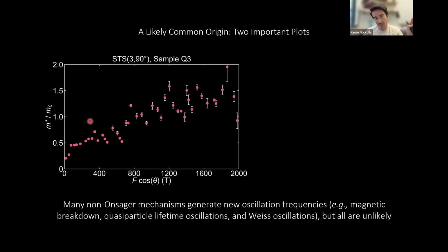There are many of these that are detailed in our supplement, and nearly all of them have very distinctive signatures in effective mass. So if I were to generate 45 different new pockets from magnetic breakdown, I would expect the effective mass of those pockets to skyrocket up to 45 bare effective masses, or plummet down to 1/45th of an effective mass. And we're not seeing that. So effectively, what we're seeing are normal Fermi pockets in these measurements, although it's a really chaotic, complex band structure.